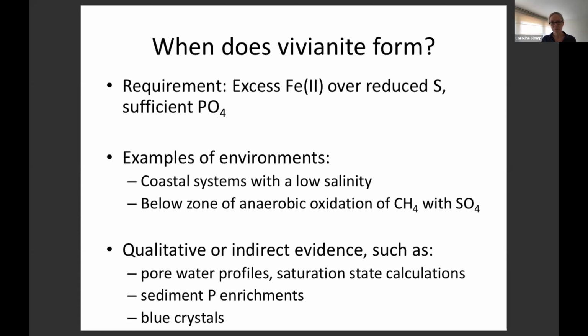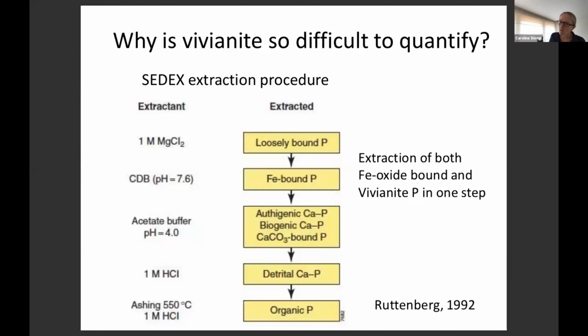Next slide, please. And so why is Vivianite so difficult to really quantify and really prove that it's there? Well, essentially, as was just shown, we like to use sequential extraction procedures to determine Vivianite concentrations. And if we look at the one that's most used for marine sediments, the so-called SEDEX procedure developed by Kathleen Ruttenberg in 1992, we see that the second step targets iron-bound phosphorus.